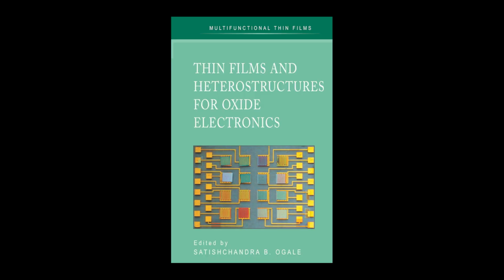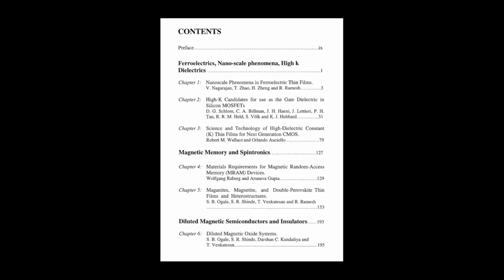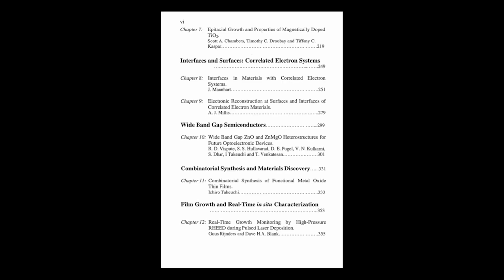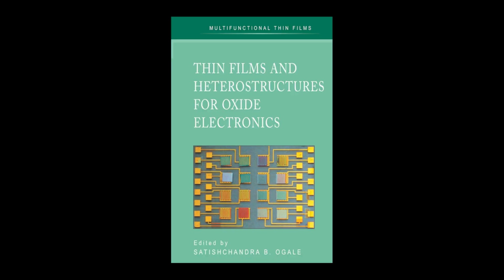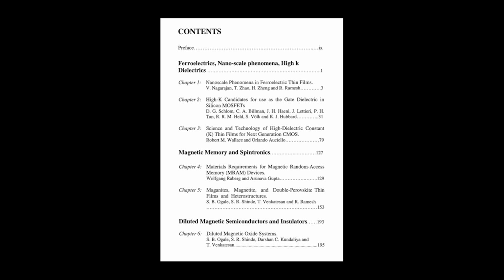And having that real-time kinetic information actually enabled a whole new way of growing films. The source calls it pulsed laser interval deposition, or PLID. PLID is really where real-time monitoring enables atomic-level engineering. The RHEED monitoring showed that after a typical fast PLD pulse deposits material, those atoms need a certain amount of time and interval to relax, diffuse around on the surface, and find their proper crystal sites before the next pulse arrives. Okay, they need time to settle down.